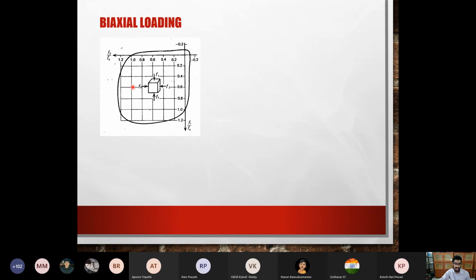You didn't tell it exactly, but I get your idea. Basically what he's saying is, when you compress it in this vertical direction, the lateral direction will be unrestrained when you don't apply a load in the lateral direction. If you imagine the cylinder, it's going to expand and it's going to have failure. Now, when you apply a compressive load in this lateral direction, it is going to restrain and prevent the lateral direction from expanding or from failing. It's going to press it back inside. Okay, so the cube is there. When it's being compressed, it's trying to expand a bit. If you apply a compressive load in this direction, it's going to push it back inside. It is countering your failure. So that is why the apparent strength which you get will be higher if you do a biaxial compression test.